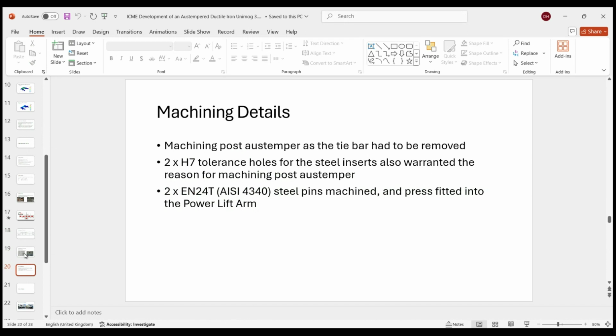after the heat treatment. Another reason it was machined after heat treatment was due to the fact we have this tie bar that you'll see in a minute. Obviously, we have to have the tie bar to stop the arms closing in the heat treatment, so that has to be taken out after the heat treatment. So as you're doing that part of the machining, it was decided that all the machining would be done after the heat treatment. There wasn't that much machining. There were obviously the holes for the pins to go through, and then a couple of H7 holes in which their steel inserts were forced into. Okay.